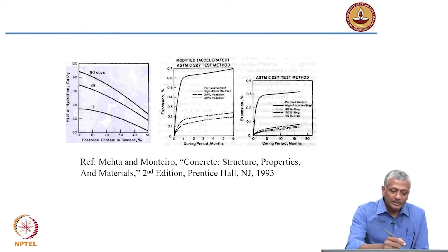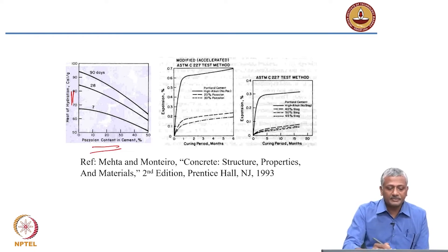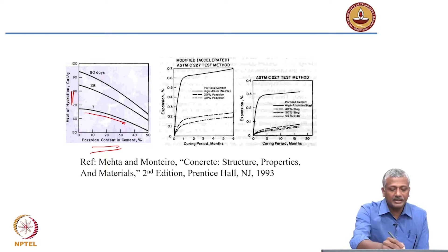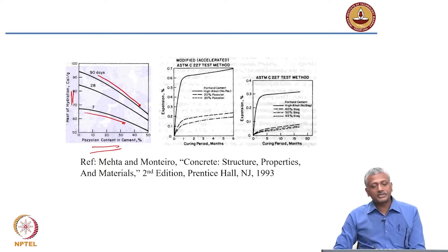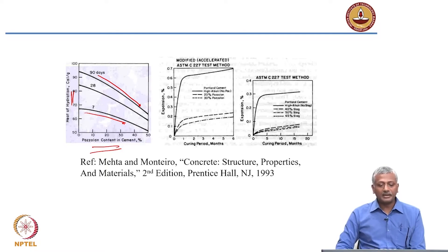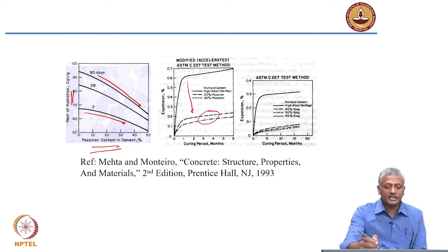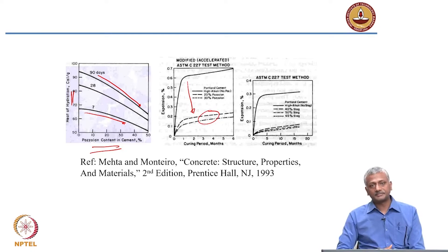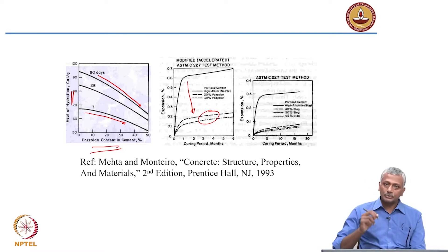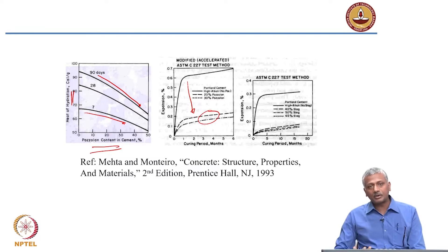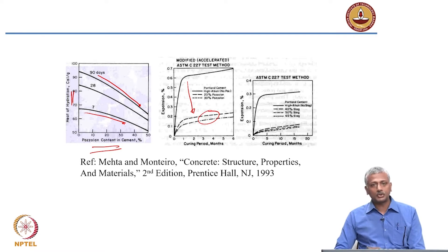This graph shows the heat of hydration in calories per gram with respect to pozzolan content of cement. At 7 days, there is a small reduction; at 90 days, the extent of reduction of heat of hydration is significant. In certain cases where you have problems of undue expansion of concrete, the use of pozzolanic materials brings down the expansion and reduces the tendency for cracking. Overall, today we increasingly have to prepare concrete with cementitious additives that are pozzolanic in nature to ensure much better long-term durability.